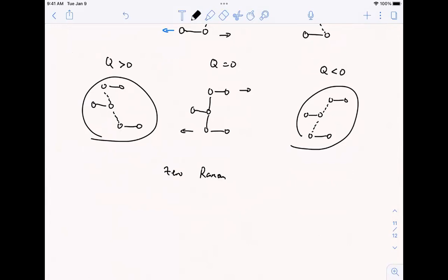Particularly here, we're considering when the electric field is on the XY plane. And this is our geometry in experiment. It's the normal one that you use here. You shine the light vertically, then the electric field will be in plane. And the in-plane electric field won't be able to differentiate which way they're tilted.